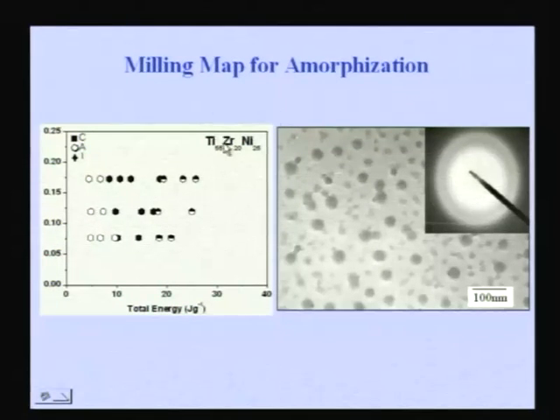This is another ternary kind of a glass where a nanocrystal becomes a glass after a certain period of milling, and again here also you can see there is a minimum total energy beyond which you get a glass. But interestingly you can see that here also you see these half filled circles, which means that the amorphous phase that has formed in this domain crystallizes when you put in very high energy. This is also another interesting thing.